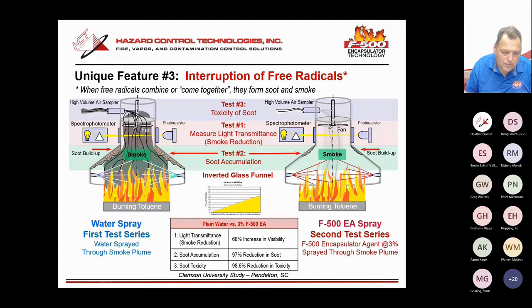68% increase in visibility because we had a huge drop in the amount of smoke. So way more light was going through. The soot accumulation was 97% less, and the soot toxicity, what got sampled from the air sample, was 98.6% less, a reduction in toxicity. So I know we're talking about lithium-ion batteries here, but here in the US, we're seeing a big movement of utilizing this agent because of what it does to improve the IDLH environment and take away the toxicities that are causing cancers to firefighters.